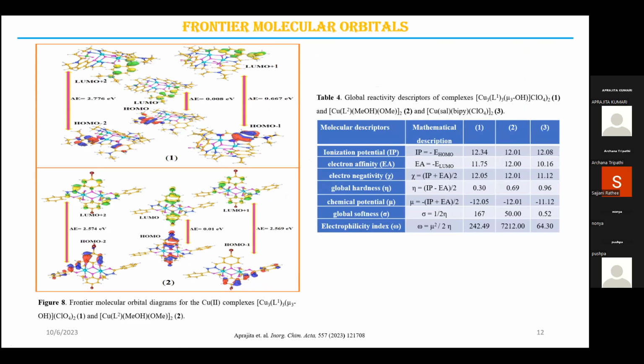Yeah, so we have studied the DFT for all the complexes, and we have the HOMO-LUMO energy gap for the complexes. As we know, the HOMO-LUMO energy gap tells us about the chemical stability or chemical reactivity of the complexes. We have found that the energy gap for complex 1 was least, which shows that the chemical reactivity of complex 1 was higher than the other two.